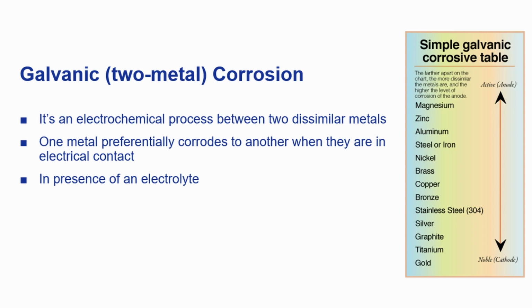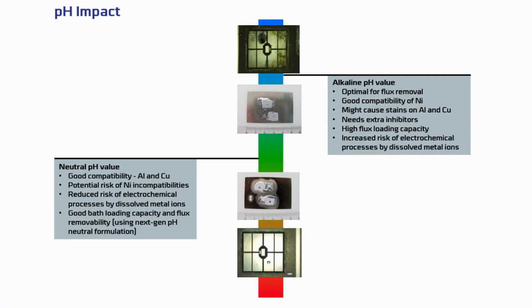So in such cases, especially power electronics, it's really important to use the right chemical and the right cleaning equipment, because the chemistries need to have good corrosion inhibitors in their formulation, which will avoid any kind of galvanic corrosion related failures. The failure mechanisms that we come across with this type of components are electrochemical migration, then corrosion-induced leakage currents, and in the case of semiconductor electronics, we have to look at the bond strength, the shear strength, and such factors.